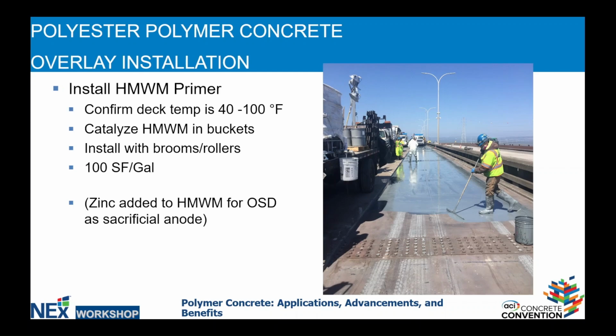Now, it can be rougher, and of course, the rougher that surface, the more material gets consumed in an overlay installation. But you don't want it too smooth, because not only are we looking for a chemical bond, but we're also looking for mechanical interlock. We're looking for an open textured, very porous concrete that allows that primer to kind of sink in and absorb and create a beautiful bonding bridge for the compatible overlay that follows.